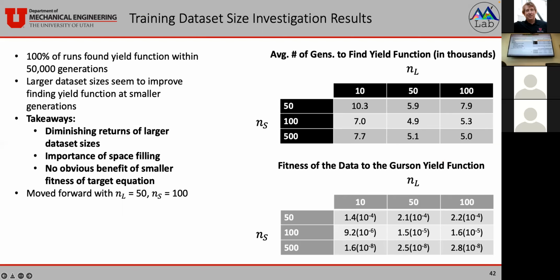Okay, moving on to the training data set size study. We saw 100% of the runs recovering the yield function in this study. Larger data set sizes did seem to improve upon finding the yield function. They found it at earlier generations than using smaller data set sizes. But again, there were diminishing returns. So, using tons and tons of data is not necessarily going to give you better performance. So we found a happy medium using 50 load cases with 100 steps each.